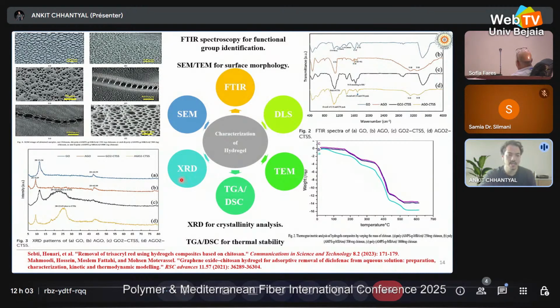Most of our polymers are crystalline, and it can show the peak like this. But if it is graphene oxide nanomaterial, it shows some peak like that. That's the reference. And the TGA and DSC analysis mainly focus on the thermal stability by comparing the percentage decrease in weight with respect to temperature, or the heat with respect to temperature. And these are the characterizations which involve the hydrogel, but there are some other characterizations that involve NMR and other things. If we are synthesizing the monomer from organic synthesis, we can use that in the process.